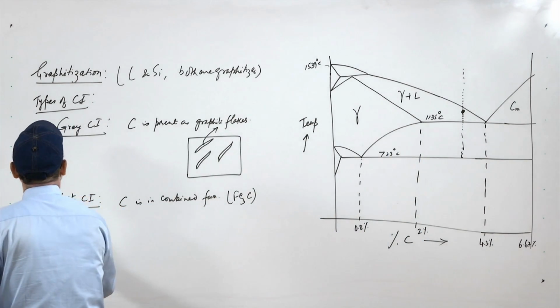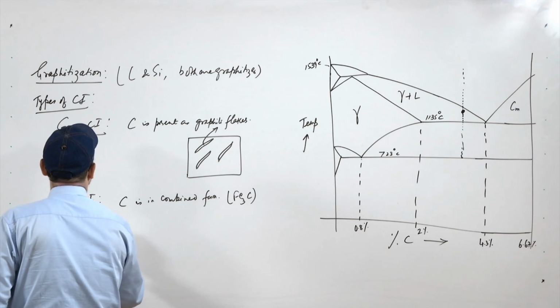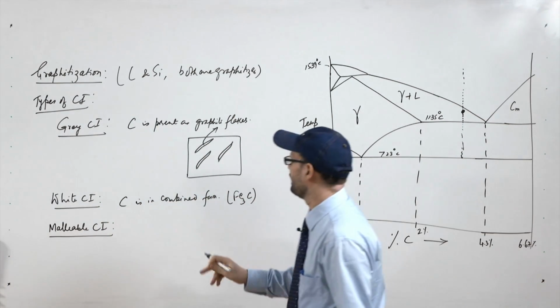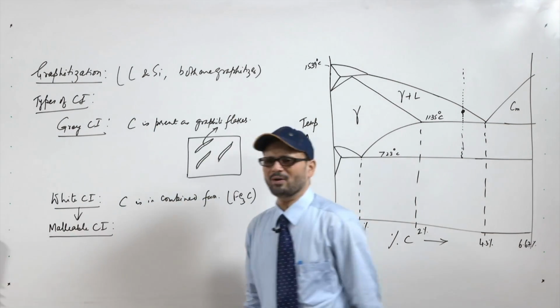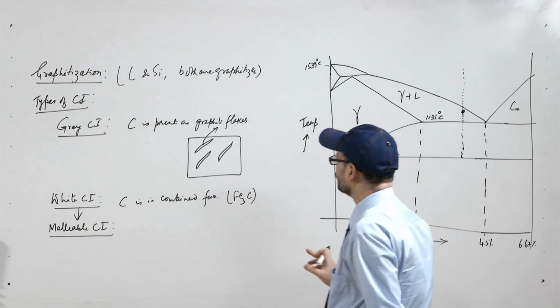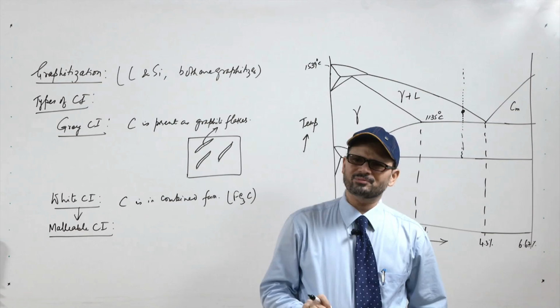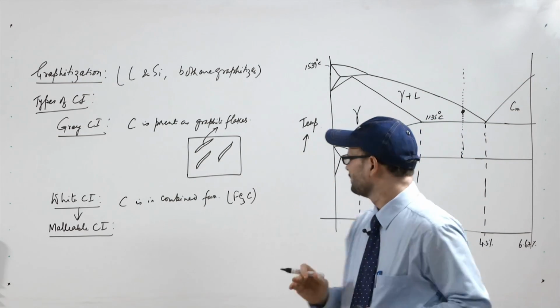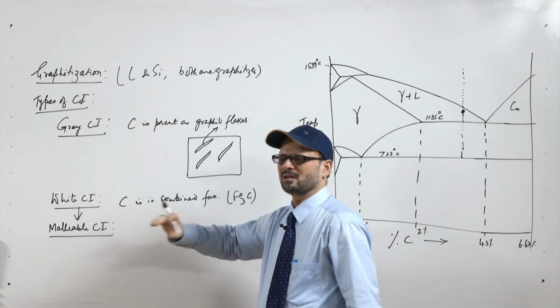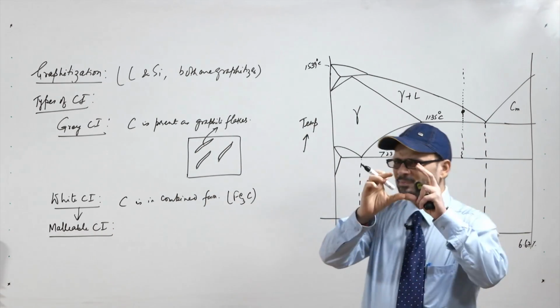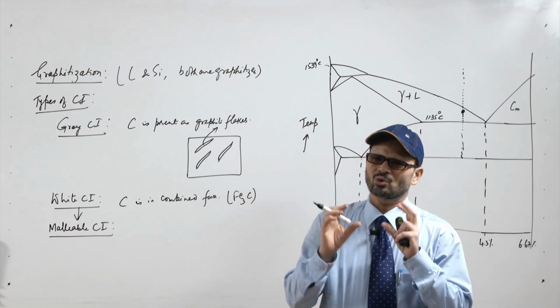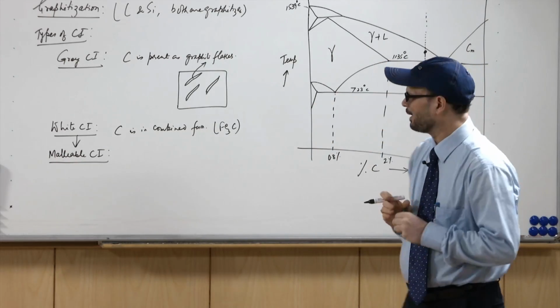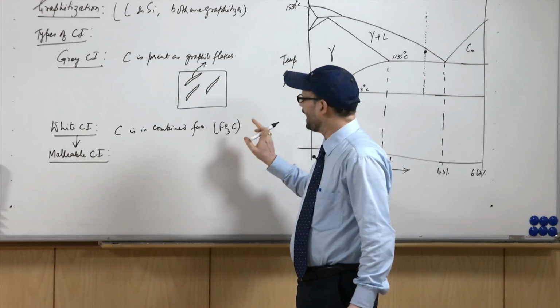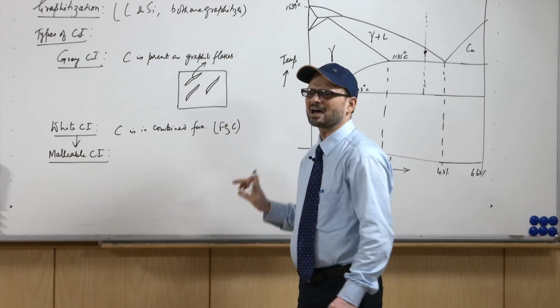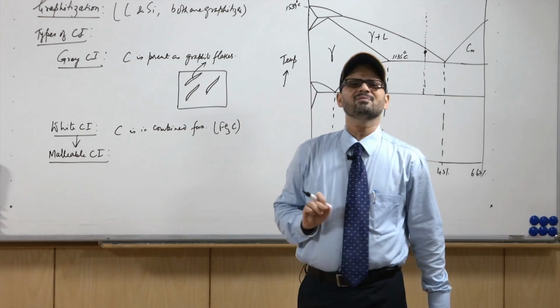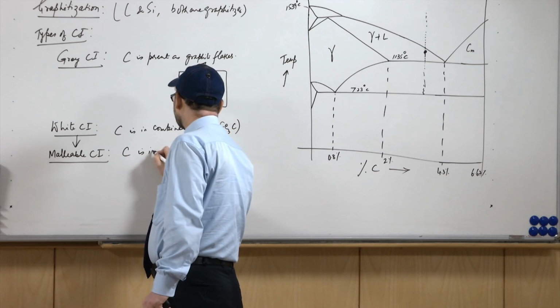There is another variety of cast iron, that is malleable cast iron. This you get from white cast iron. Since white cast iron is of no use, we do heat treatment: we heat it and hold this white cast iron at a temperature more than the transformation temperature, and at that temperature we hold for a very large time. Due to holding for a large amount of time, this decomposes to iron plus carbon. This carbon is released as free carbon or temper carbon. So, in that case the carbon is in temper form.